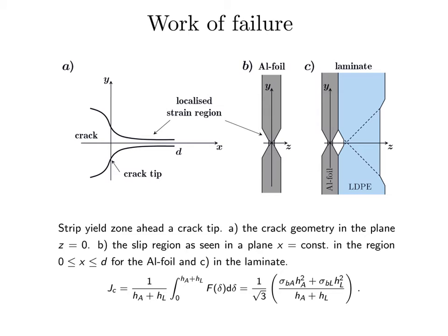The present study that I'm going to talk about is about either of these two, it doesn't matter which one, and the influence that buckling may have on this. As you see in the equation below, it's very easy to calculate the energy release from a cohesive zone like this, and it is a force. It acts as a force between the surfaces of the upper and lower parts of the specimen, and as it increases, the cross-section decreases, and if the material is, let's say, perfectly plastic, then the stress decreases linearly with the widening of the neck.